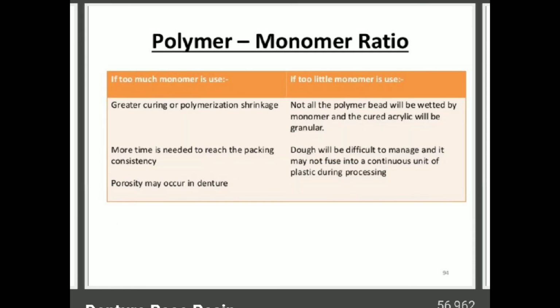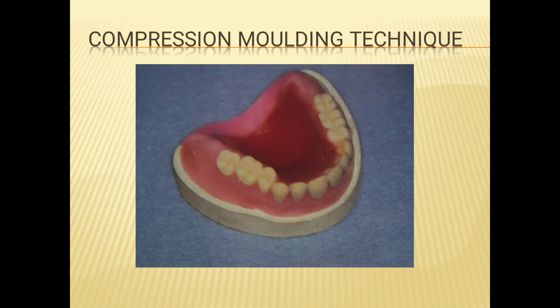That's one of the important viva questions. Then you can see what happens if too much monomer is used and if too little monomer is used. If too much monomer is used, what happens? It causes greater curing or polymerization shrinkage. More time is needed to reach the packing consistency and porosity may occur in the denture. If too little monomer is used, not all the polymer beads will be wetted by the monomer and the cured acrylic will be a granular mass. Dough will be difficult to manage and it may not be fused into a continuous unit of plastic during processing. That is if too much monomer or too little monomer is used.